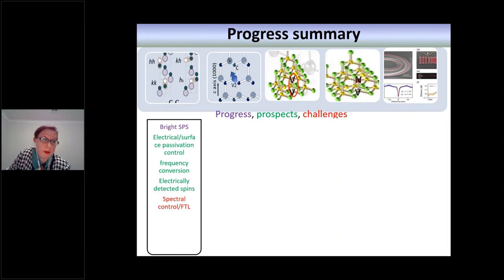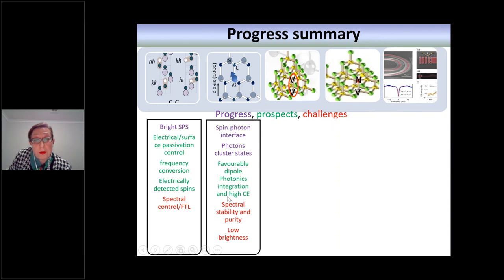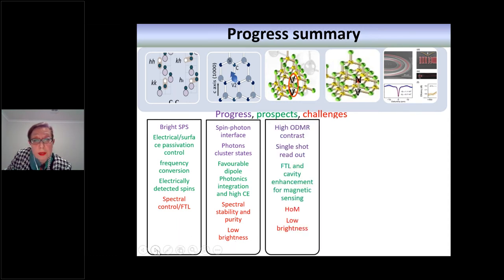So let's say that perhaps each color center may have a specific application and challenges. For instance, the visible emitters are bright, can be controlled electrically by surface passivation, and it's possible to achieve frequency conversion, and potentially it's possible to achieve electrical detection of spin in these defects. However, the challenge of achieving indistinguishable photons could be quite big. And for what concerns the silicon vacancy in silicon carbide, this seems to have the best outlook in terms of properties of a single photon source for a spin photon interface. However, the challenge could be that this is still a low brightness emitter.